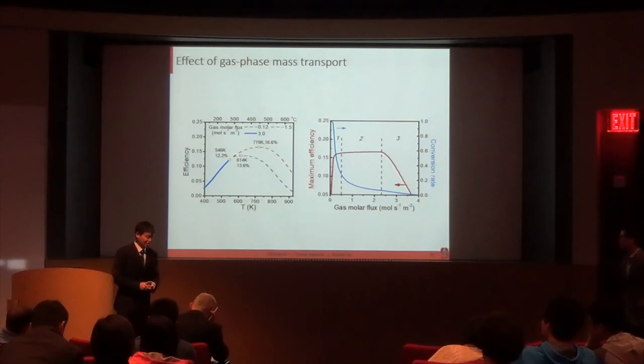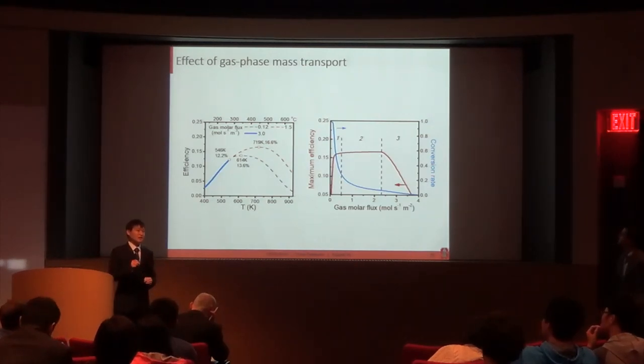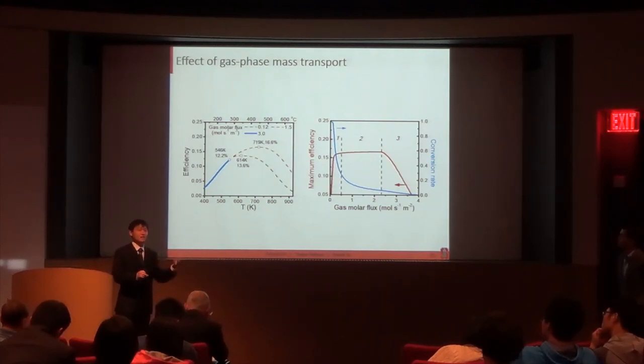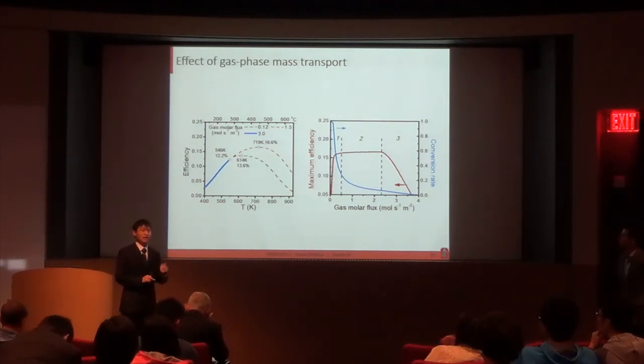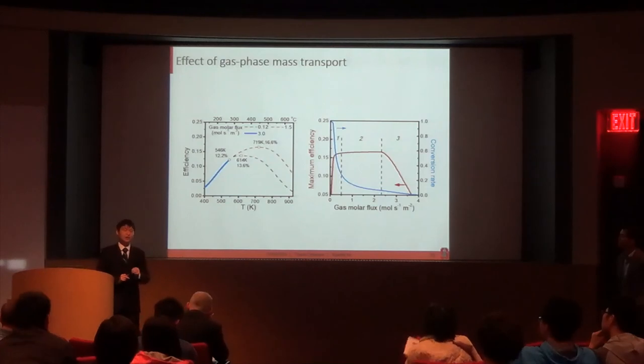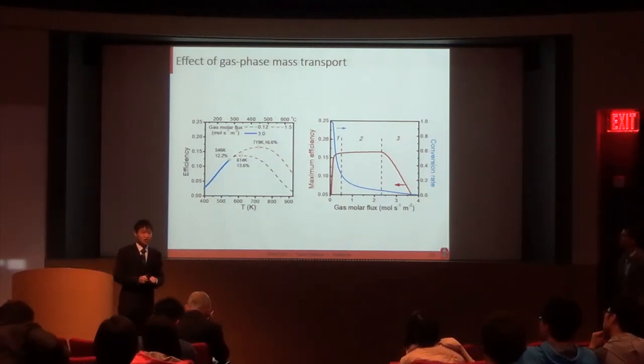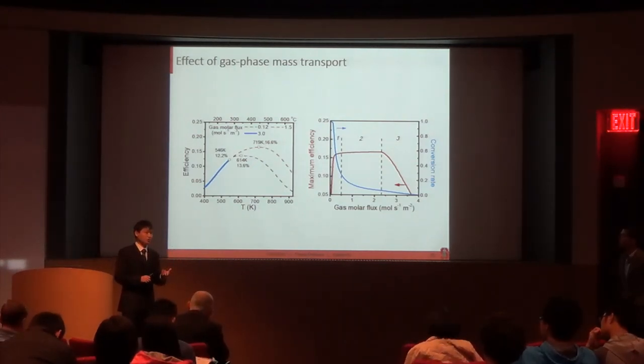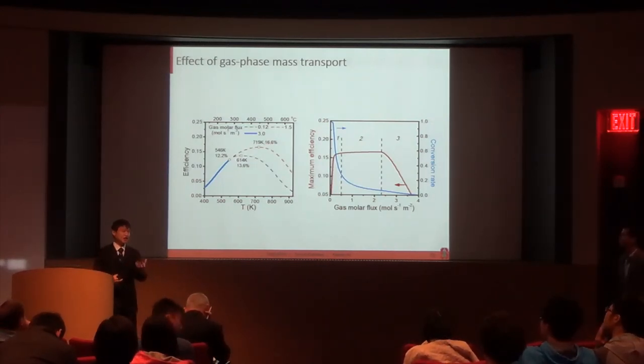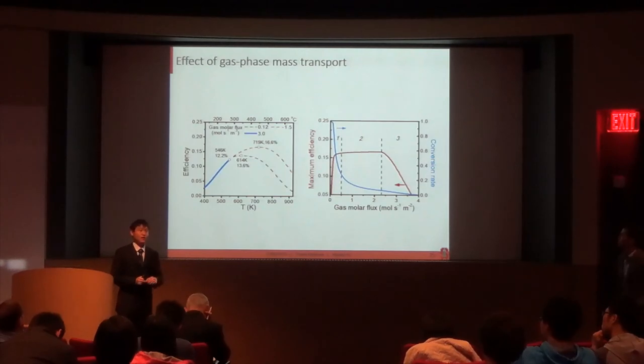That's a very good question. So without illumination, I believe the bismuth vanadate is stable under these photoanode conditions, so oxygen environment, 400 degrees Celsius, because these materials are annealed or synthesized at such high temperatures, or even higher temperatures, in air. But under illumination, it is a good question, as I do see some degradation for the BVO at such high temperatures. So under illumination, there might be some corrosion on the surface with a gas, or maybe some additional side reactions happen at the surface. But at this point, I don't know what's going on there.